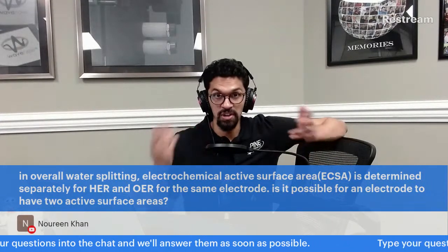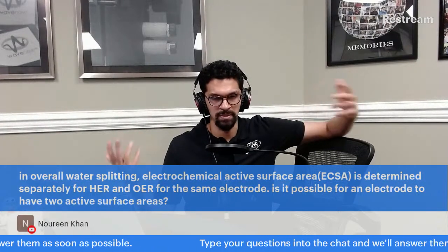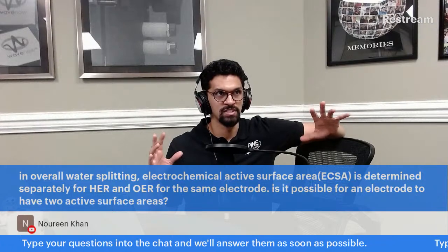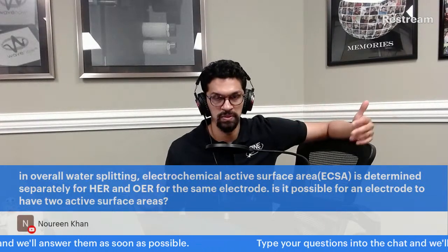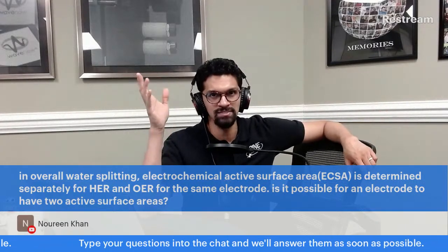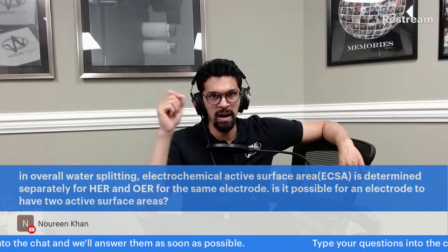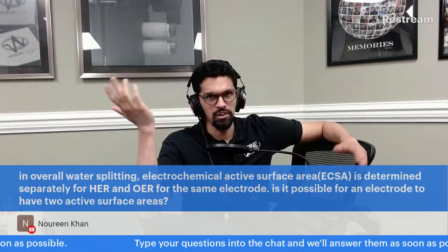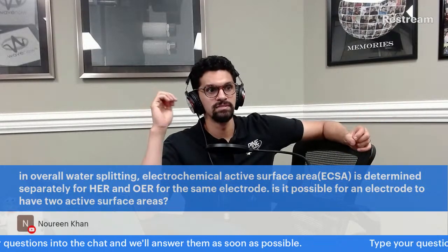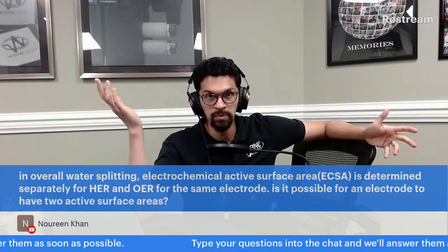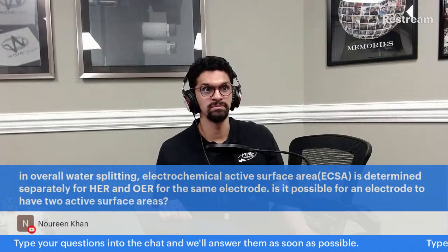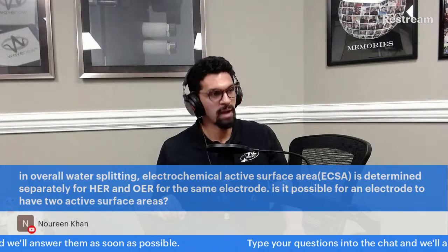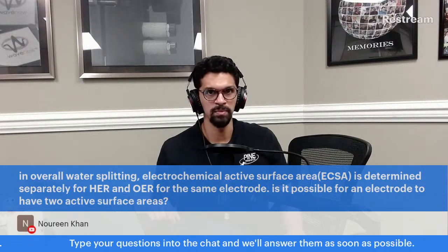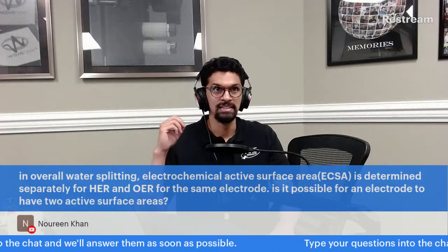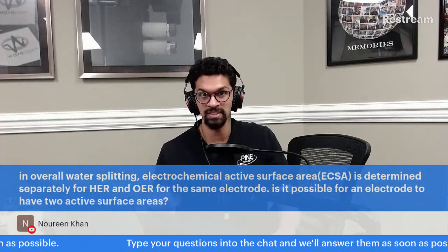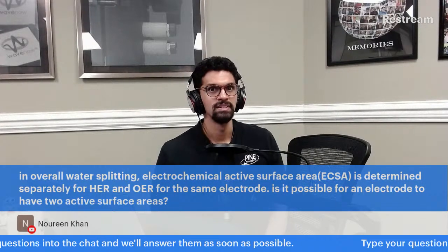So in principle, the answer is no. There are not two separate electrochemically active surface areas. Well, I should say that differently. There's only one area for the electrode, but you might have more than one active area for a particular analyte that's bound to a certain species. So for example, let's say you have polycrystalline platinum. Well, maybe there's a special reaction that only occurs on platinum 111. And then there's another reaction that occurs on platinum 100. Well, the amount of exposed platinum 111 and the amount of exposed platinum 100 may be different, and hence the measured electrochemically active surface area for that specific thing may be different. That may be a possibility.